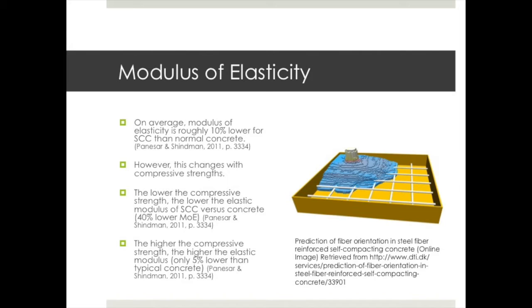It has also been found that at a lower compressive strength, which is approximately 20 MPa, the elastic modulus of SCC can be calculated at 40% lower than normal concrete, but at higher strengths, which is approximately 90 to 100 MPa, the elastic modulus difference is reduced to only 5%.